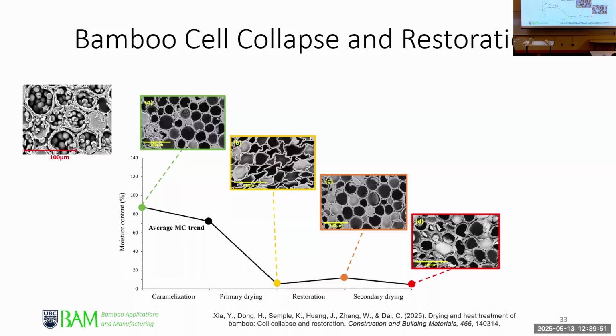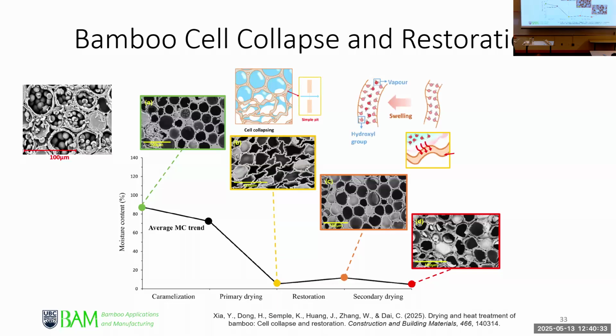you dry. Mind you, during drying, we also have to go through a carbonization or caramelization process. The bamboo tissue is heat treated to make it more mold resistant. Mold is common in bamboo because it contains starch, like you see in this. And then that has to be treated or removed and heat treated, along with drying. So at some stage during the primary drying stage, the water is removed and you create a vacuum basically because it's so small. The vacuum pressure is too high for the cell to hold and the cell starts to collapse. And then you gotta go through a secondary steaming process to recover the cells.